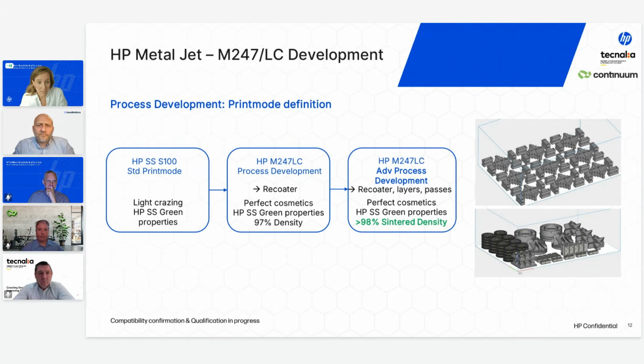And with the third printed job, we made a bit of change on the recoater, layer thickness, and the strategy on the passes. And we confirmed together with the Tecnalia team that just with the sintering at high vacuum, we got results above 98%. As I said at the beginning, it is kind of nothing new because we did it before with our stainless steels and with our diagnostic parts plot layout that you have on the top of the figures.